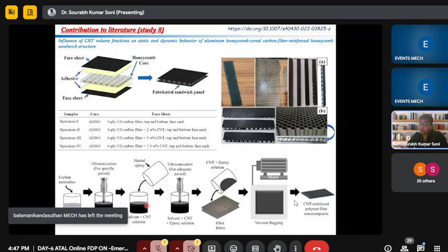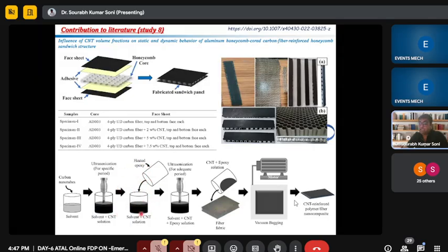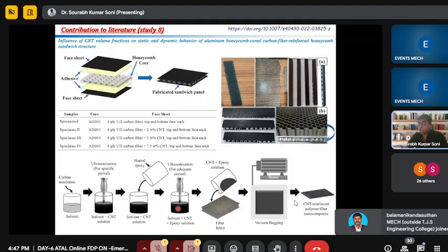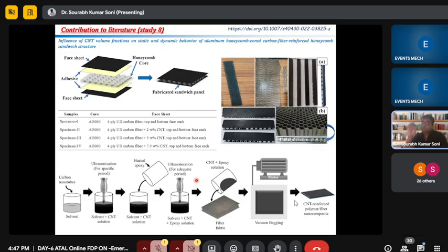We will mix the heated epoxy into the CNT solution, and then again sonication, because if we sonicate the CNT alone, it will behave differently. If we mix the epoxy and CNT and then perform the sonication, it will behave differently, because the epoxy is a very gummy kind of liquid. In a gummy liquid, the CNT will be fixed and very rarely affected by the ultrasonication. So we must follow this process very carefully.